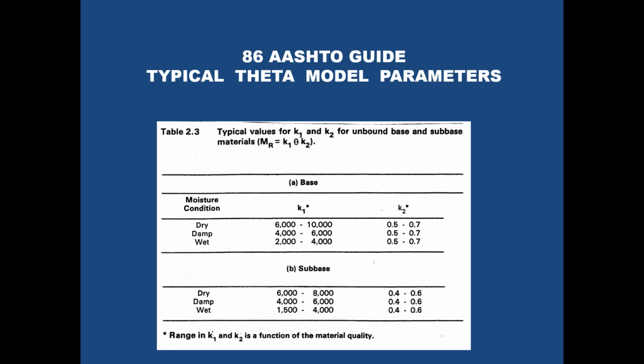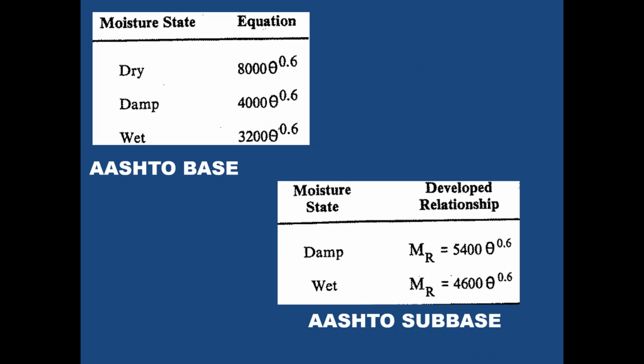Okay, these are some suggested values for theta from the 86 AASHTO guide. They have values for K1, K2, for base and subbase. A ballpark value a lot of people use is 5,000 theta to the 0.5, where all the inputs are in psi. This is AASHTO base, AASHTO subbase. They're looking at some suggested interim values that might be appropriate.